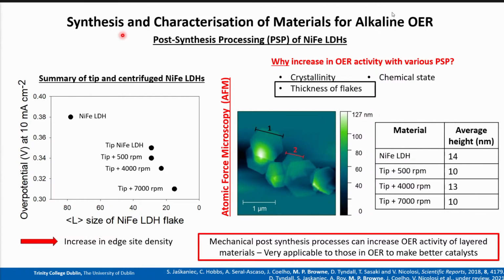So essentially, what is happening is that it's really simple. The fragmentation is causing an increase in edge site densities, which improves the OER, which also tells us that the OER is preferential to edge sites and not the basal plane sites. So the reason that I wanted to show this research in particular is because anyone in OER catalyst research can use these methods to try and increase their OER activities, as well as the chemical means that are currently used.